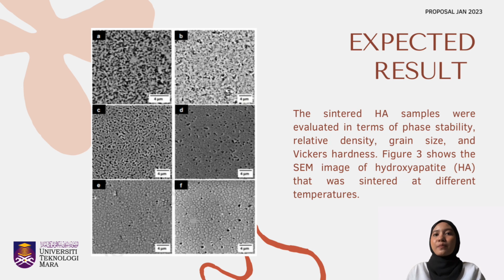The sintered HA samples were evaluated in terms of phase stability, relative density, grain size, and Vickers hardness. Figure 3 shows the SEM image of hydroxyapatite that was sintered at different temperatures. It shows the microstructure evolution of sintered HA at A, 1000 degrees Celsius, B, 1050 degrees Celsius, C, 1100 degrees Celsius, D, 1150 degrees Celsius, E, 1200 degrees Celsius, and finally F, 1250 degrees Celsius.